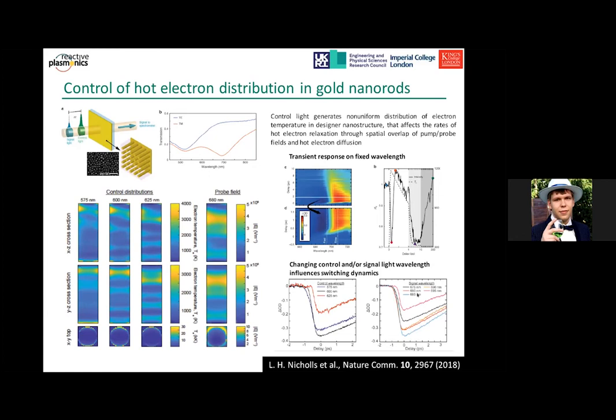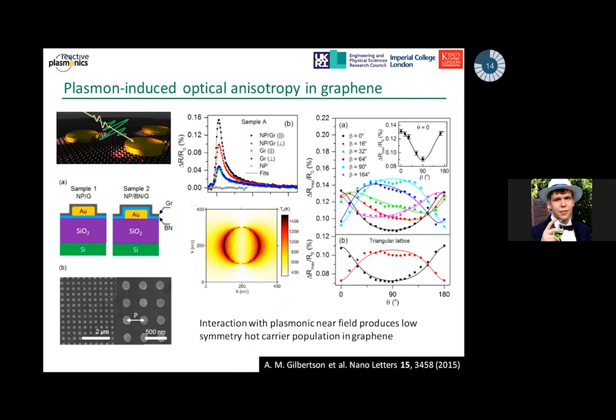A similar idea, but entirely different realization, was used to demonstrate a plasmon-induced optical anisotropy in a graphene layer. For this, we made a square lattice of cylindrical plasmonic dots on top of graphene. This structure is in-plane isotropic, or more precisely has a fourth order rotational axis, which is too high to be observed in linear optical response or even in nonlinear second order optical response. Therefore, anisotropy is not expected under the normal incidence.